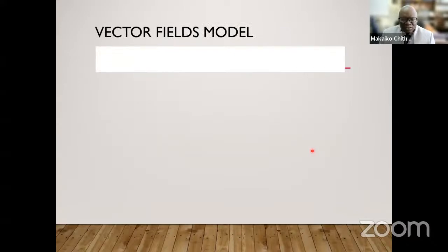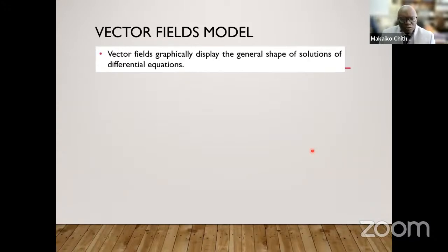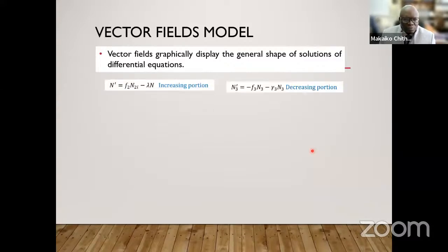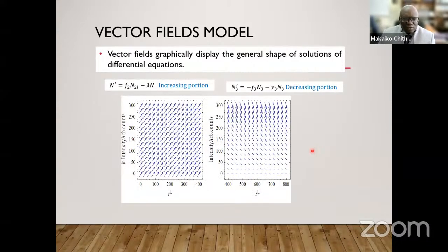Another way, if you don't know the number of donors, you don't know the number of acceptors, but you at least have a general idea, is to use vector fields, because with vector fields, you don't actually need a solution to a differential equation. If we use a vector field model for the increasing portion and the decreasing portion, we can see that the prediction of the solution is that it will increase with time initially, and it should decrease later with time.